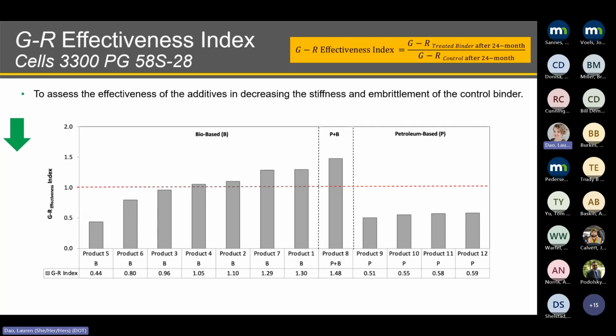So basically, we want to see the effectiveness of these additives in really changing the embrittlement and stiffness of the binder. So we want these results to be lower than 1. That would mean that these treatments are really working against the stiffness and embrittlement of the binder. As you can see here, some of the bio-based products would pass this criterion considering the Glover-Rowe parameter, while the petroleum-based products would all be classified as effective.